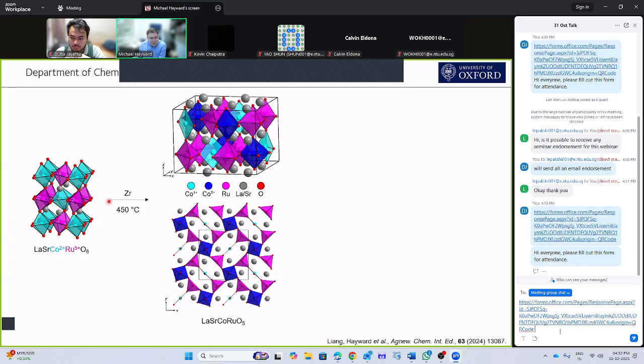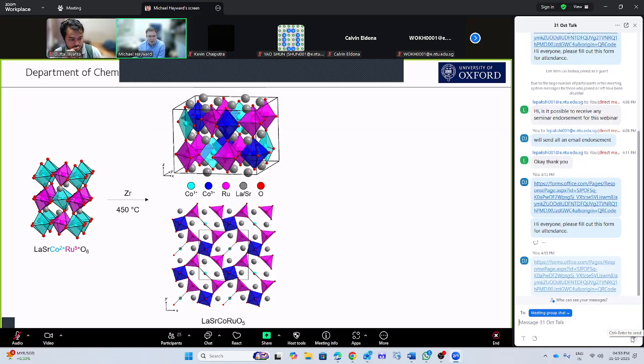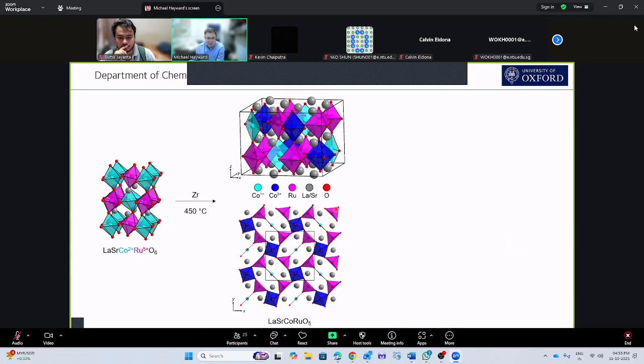Well, yes, we can if we start using reducing agents that don't contain hydrogen. So here's a good reducing agent that doesn't contain hydrogen. So this is zirconium. And we find if we treat this material with zirconium, we can make this oxygen deficient phase, LaSrCoRuO5, which has a rather interesting and elaborate structure.